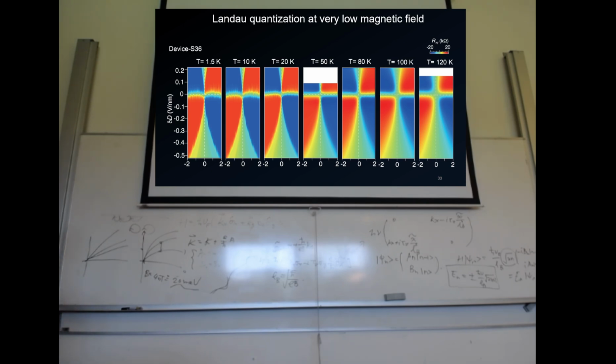It prevails to a very high temperature, and this is what we were discussing before, that at 80 Kelvin, which is right above the liquid nitrogen temperature, we will have a quantized plateau at 0.3 Tesla. So 0.3 Tesla means if you go to Amazon and buy a magnet, the surface magnetization strength can sometimes be larger than this value, 0.3 Tesla.